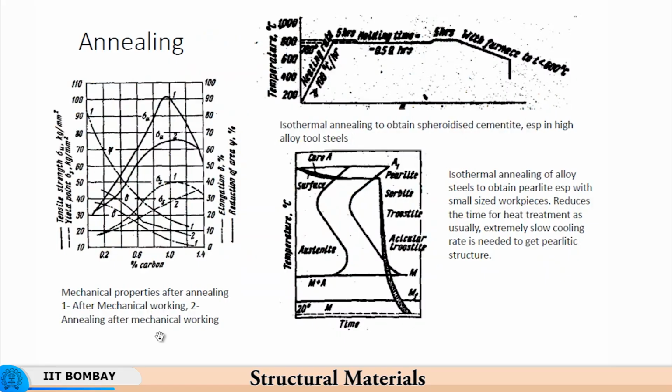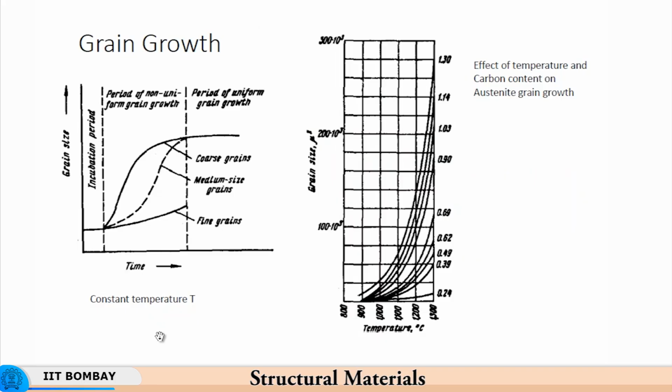Now, if you look at the annealing using different properties, you have very high strength after mechanical working, okay, and then after annealing the strength comes down quite significantly, and therefore, the ductility tends to go up very significantly after annealing. So, this is what we have found.